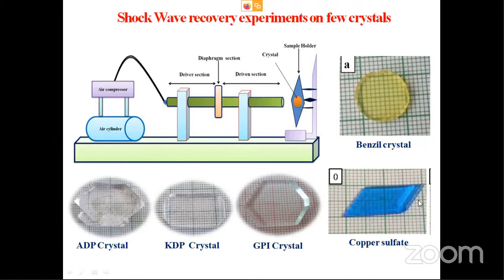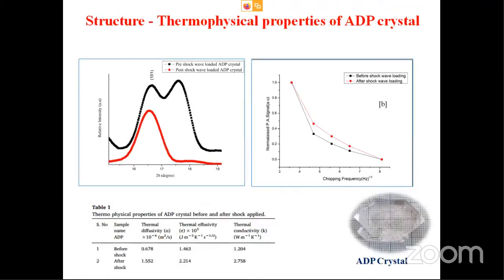You can see I'm showing two photographs of this crystal. What we have done, we have taken an ADP crystal, ammonium dihydrogen phosphate crystal, that is ADP. A single crystal we took, and we have given one single shock, and we have taken the XRD. What is happening? You can see this is the control. It has two peaks. It is called a twin peak.